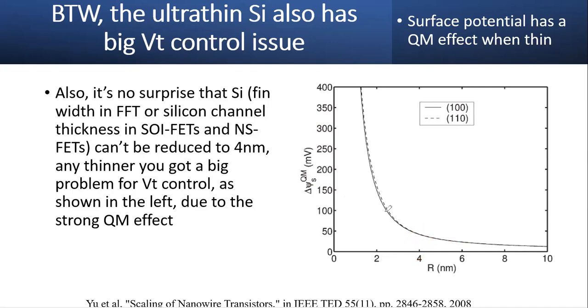I'm a process guy, so you can see that if you have, say, 3 nanometer, then your process, of course, has roughly 1 angstrom variation. Then your VT will change by 100 millivolts. How can you control that? My VT for high-end CMOS is like 0.2 volts to 0.3 volts, and then my VDD is only 0.7 volts. I have no room for this large variation.